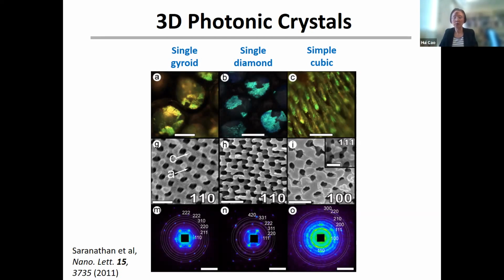It seems that they are using a different approach than what we usually do. Typically in the lab, we try to make periodic structures. We first synthesize building blocks, like spheres of the same size. Then we self-assemble them to form periodic structures. But right now we can only get a face-centered cubic from this kind of self-assembly. But in nature, all these kinds of structures are created. So they are using a different strategy than what we're doing.